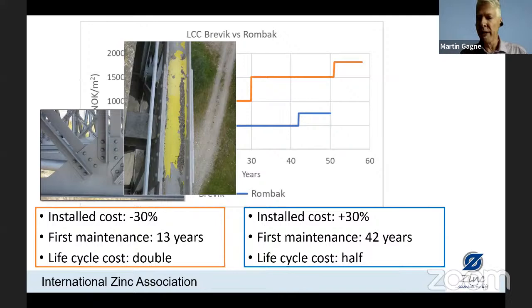But when we put it immediately in a 100% humid salt spray test, those protective layers never get a chance to form. And so if you are just comparing salt spray test of paint and zinc, the paint will appear to be performing better than the metallic zinc coating. But all the evidence we have from real life examples, zinc metallic coatings by far outperform paint only coatings. So just a warning to be aware that not all laboratory tests can be extrapolated into real world performance.